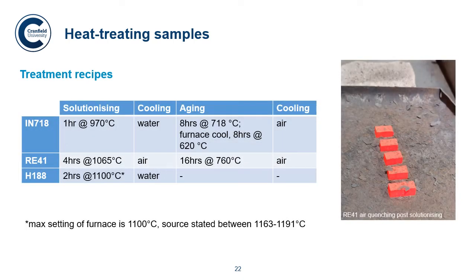So we also heat treated the samples. Inconel 718 samples underwent a heat treating process of 1 hour at 970 degrees Celsius, followed by water cooling, and then aging for 8 hours at 718 degrees Celsius, followed by furnace cooling, and then a further 8 hours at 620 degrees, followed by air cooling.